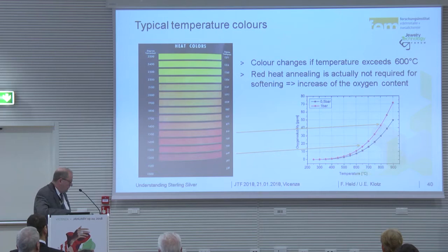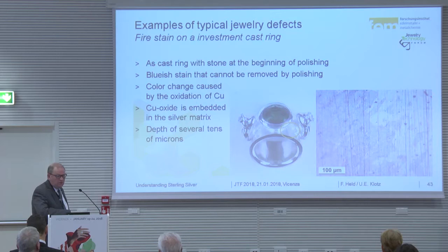An example for typical jewelry defects is the fire stain. As-cast ring with stone at the beginning of the polishing, a bluish stain that cannot be removed by polishing. Color change caused by oxidation of copper. Copper oxide is embedded in a silver matrix at depths of several tens of microns. You cannot remove it. That's a surface picture.